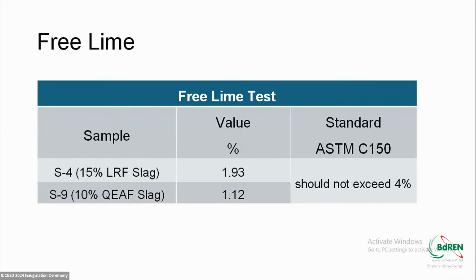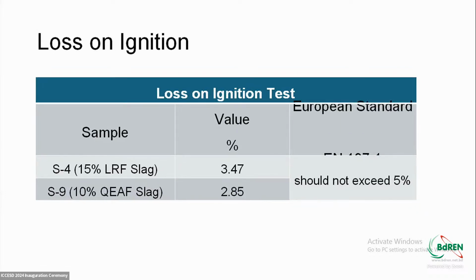In literature, we found that free lime is a problem for slag, particularly for LRF slag, but we found that for our samples, that was within limit. And loss on ignition was also within limit. So that was all about clinker replacement in cement.